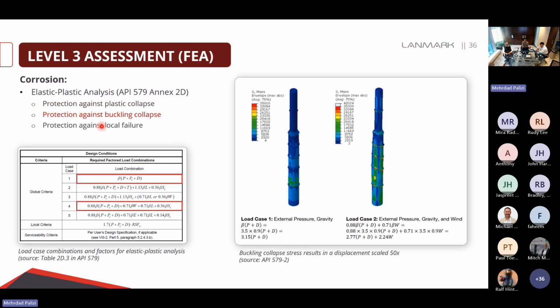The second check is for buckling collapse. If we are doing linear analysis, this is going to be very different from plastic collapse. But in the case of the elastoplastic analysis, we are basically doing the same procedure. The only difference here is that for buckling analysis, we are applying the load cases that are producing compressive stresses inside the structure. So for this example, we have the same load combinations, but instead of internal pressure, we're going to apply external pressure.